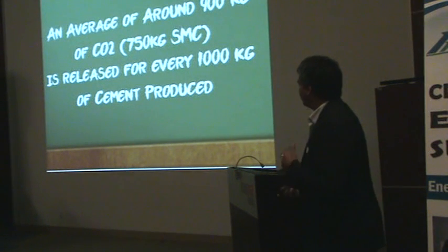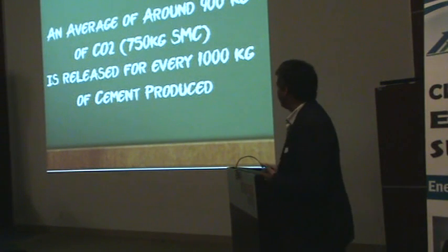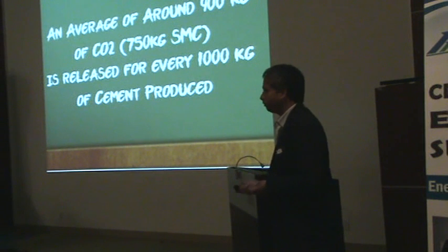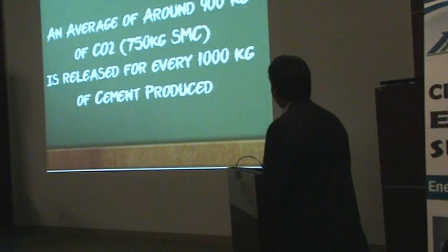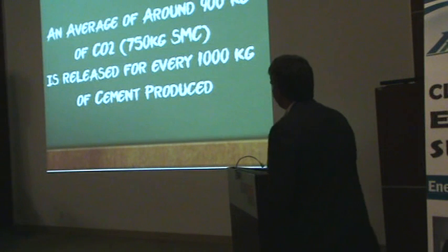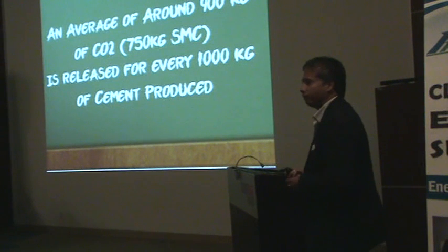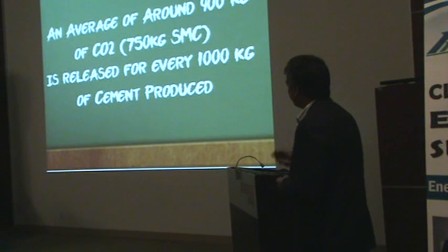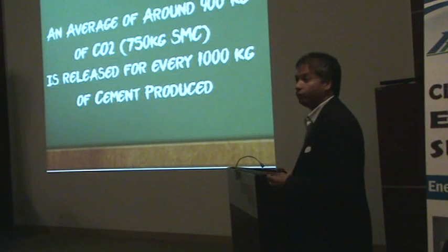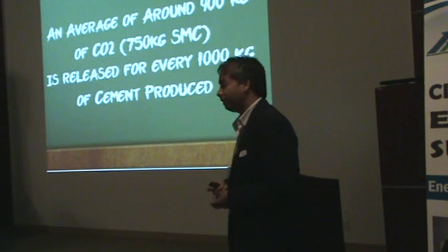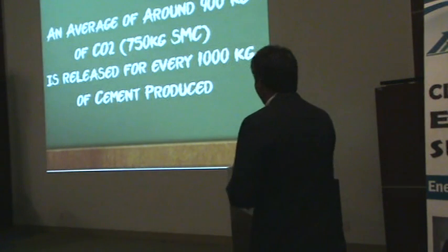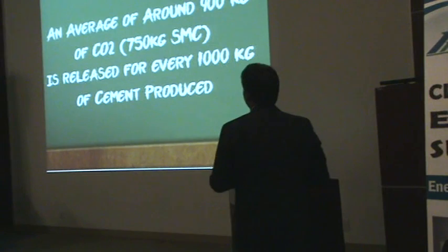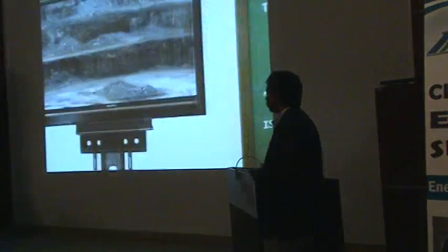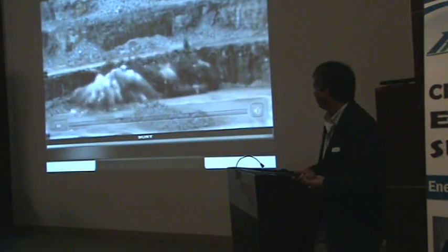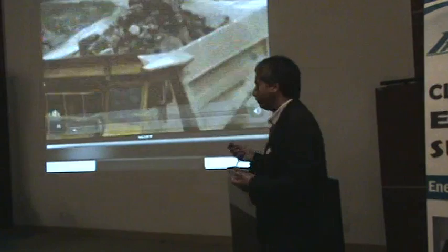The average Canadian cement plant, the average in the industry, is around 900 kilograms of CO2 per ton of cement. For our company, we operate the two lowest greenhouse gas intensity cement plants in Canada. Our average is around 750 kilograms per ton of cement. So 3/4 of a ton of CO2 goes out the stack for every ton of cement that goes out the gates. That's a huge amount of CO2, and it works out to about 5% of the world's man-made CO2 coming from cement.